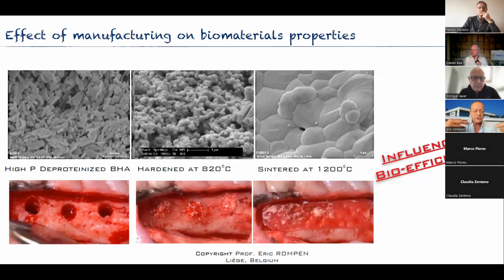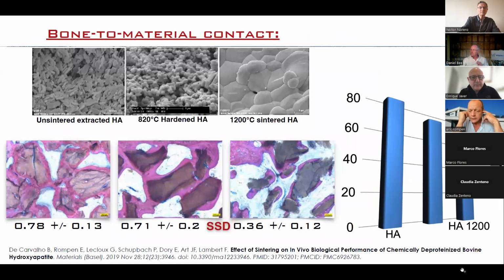Then we compared those three materials in mini pigs. And what did it give? Next slide, please. What we saw is that with the unsintered hydroxyapatite, the raw material on the left, we obtained a very high, nearly 80% of bone to material contact.